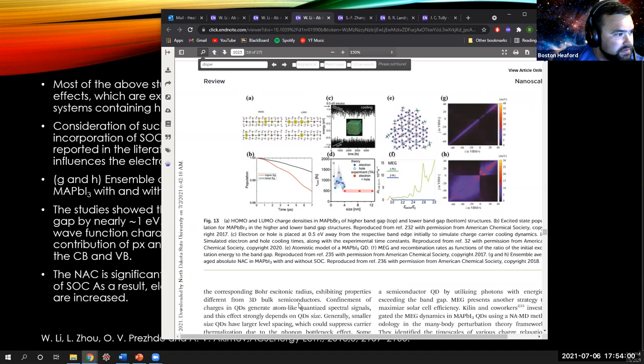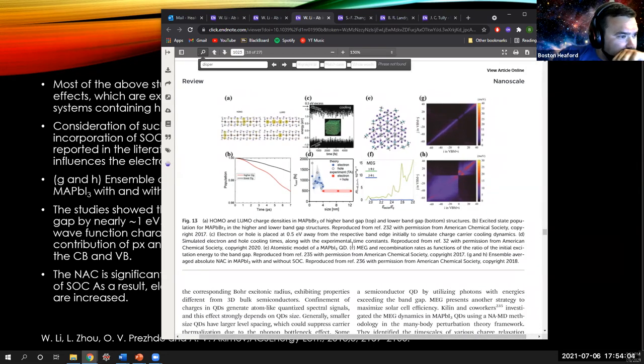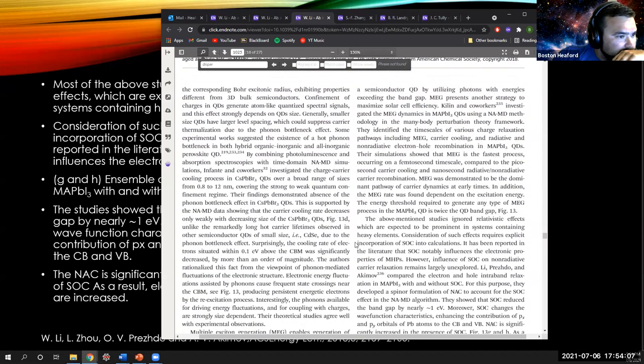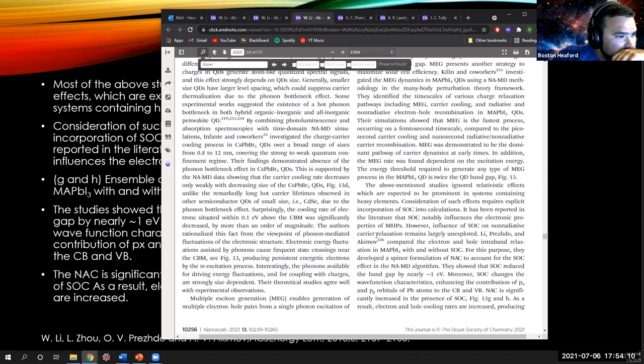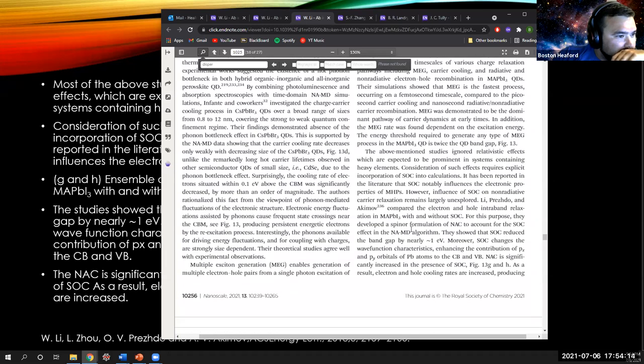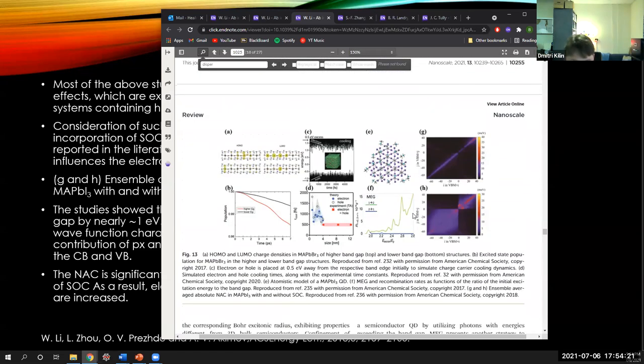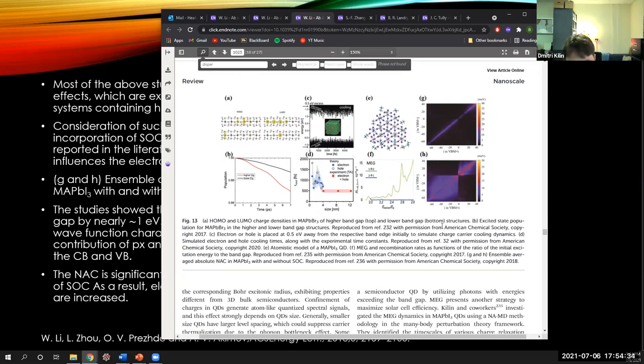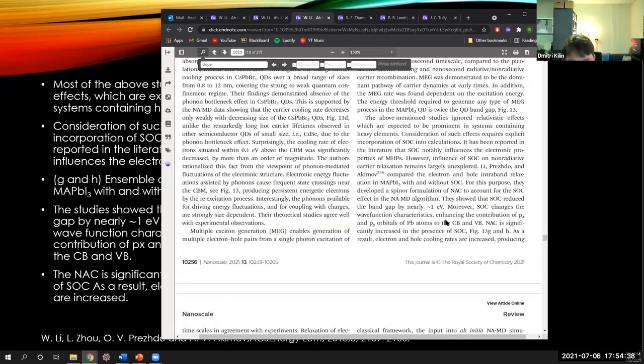Yeah, so it might have been bulk. Okay. I just assumed it was the quantum dot because it was in. No. Okay, so it is bulk, and they are telling that spin orbit coupling will speed up the relaxation. Mm-hmm. So Aaron did consider perovskite quantum dot, and he found that spin orbit coupling substantially slows down the relaxation.